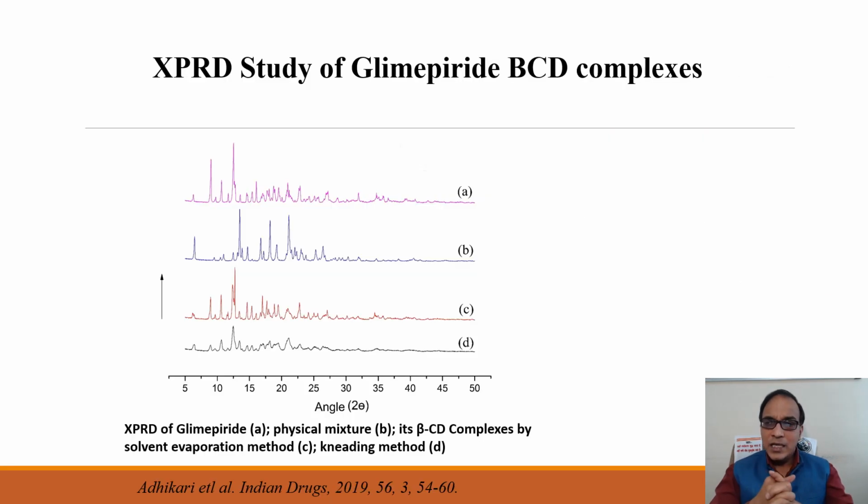Now again taking another example, the glimepiride XRPD study, it is one of our works. Again we can see the changes here, and we can also see the difference between the two methods. Here we have seen the difference between the two methods, solvent evaporation and kneading, by which the complexes were prepared, and the change in the X-ray diffraction was clearly observed here.